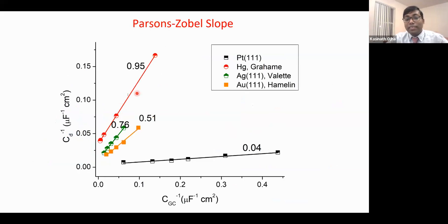So if you look at this plot, basically we call it the Parsons-Zobel plot. The experimental data matches theory only for mercury. Mercury is really a very ideal system, and it exactly matches the Gouy-Chapman theory, and that is perfect. That's a 100-year-old theory, the main theory of electrochemistry, and it's perfect. People believe it. It's nice. But silver and gold are also deviated from slope 1. That means some kind of ion association or accumulation is happening to some extent on gold and silver as well. But on platinum, it's too much, one of the extremes. In the case of gold, it is also happening to some level.